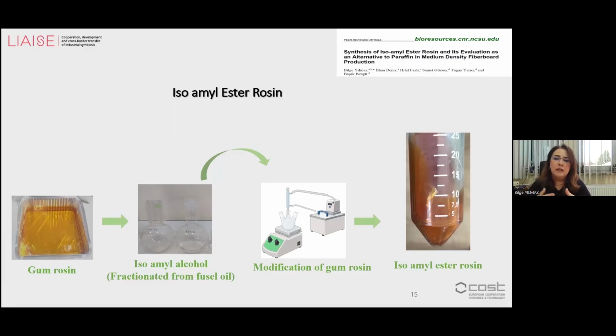You can check. We also applied for a patent for these chemicals, because the results show that the isoamyl ester rosin can be adapted to replace paraffin in the medium density fiberboard production, because you know the paraffin is a hydrophobic and petrochemical product, but isoamyl ester rosin is bio-based, sustainable, and also we can use waste to make the product. We applied for a patent, and it is also ongoing on the application.